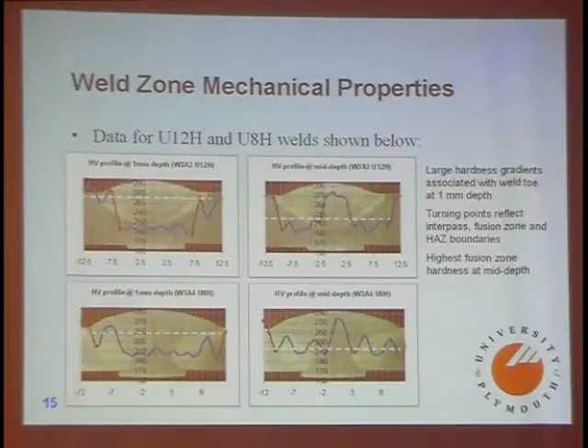Now, the sort of data you get out of this is this, and you can see that it is actually quite variable from weld to weld. This is undermatch 12 high, 1 millimeter depth, that's at the mid-profile, so that white line there tells you where the measurements have been made, and this is the profile along that line of hardness. And so they are quite variable from weld to weld. So as I say, if you've got these sensors at all at the end of the day, you should be picking up something that is true.